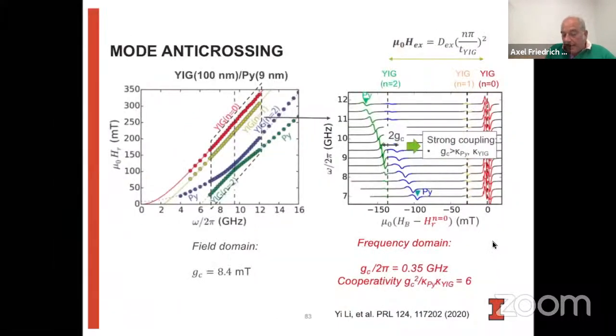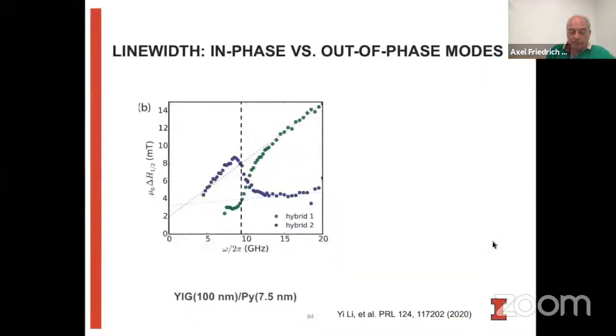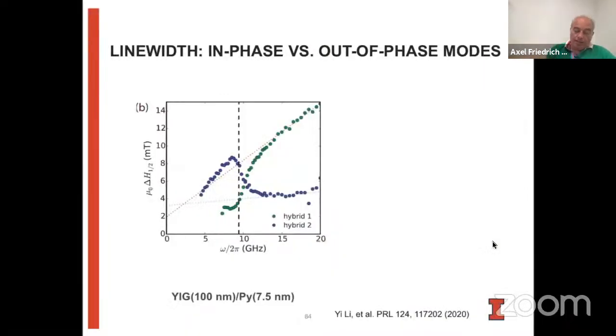Now, what is nice, by having these modes very nicely separated, is that we can actually analyze in detail the line shape and the line width of these modes as we go into this strong coupling regime. And this becomes kind of interesting. Being far away from the coupling, we can get the intrinsic dependence of the line width as a function of frequency, both for the yttrium iron garnet and for the permalloy. And in the coupling region, we see a couple of interesting features.